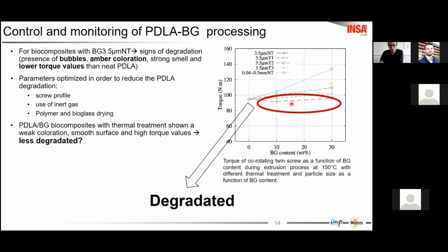These torque values correspond to the maximum values of torque observed during the extrusion process of the composite. We also observed that some biocomposites had a weak coloration, no bubbles, and high torque values. So there was a relationship between the PLA degradation and this bioglass.